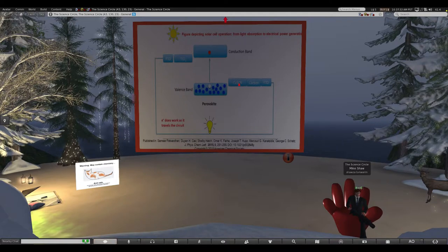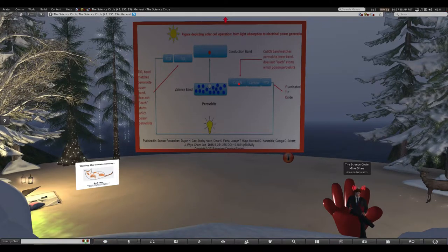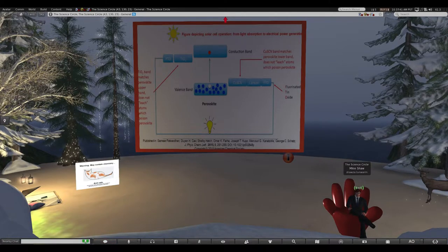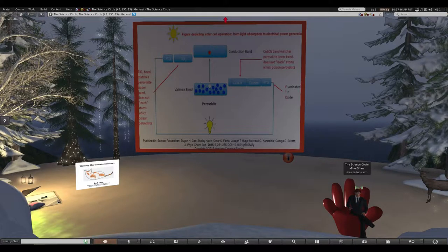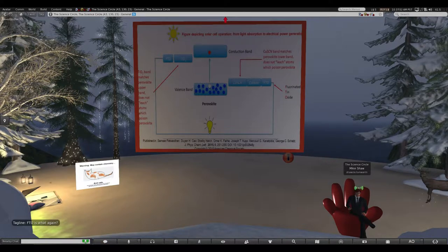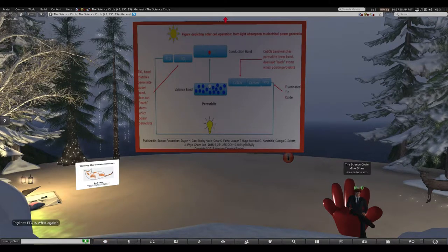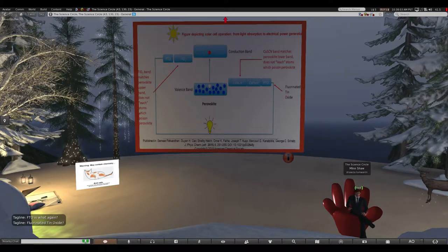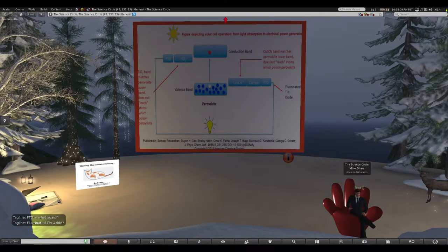Nice point about, let's see, I got some annotation here. This guy, the copper thiocyanate, CuSCN, matches the perovskite lower band, and it turns out it doesn't leach atoms into the perovskite to poison its function. The titanium dioxide has a band that matches the upper band and doesn't leach atoms to poison the perovskite. These are issues of more engineering than of the actual chemistry. But if you want a solar cell to last for years, like 25 years on top of your house, you actually have to make it so that the slow diffusion of atoms doesn't screw things up.